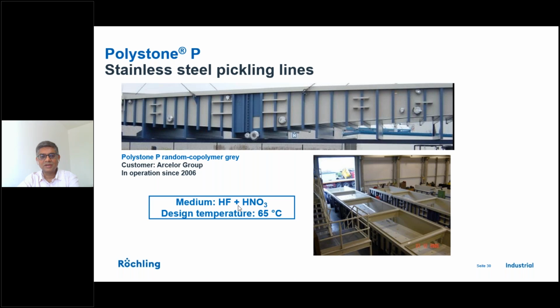This is a more complex chemistry or handling of HF/HNO3 at 65 degrees C. You can see these are the tanks which are having a sloping bottom. These are basically made from 40 mm thick sheets. In India, just to mention, we make sheets from 4 millimeter to 30 millimeter, and above 30 millimeter, we have to import from our parent company.